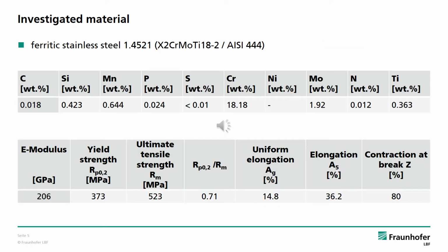This brings me to the results of the investigation. Investigations were carried out on a ferritic stainless steel 1.4521, for which I have summarized the chemical composition and material properties on this slide. With a tensile strength of 523 MPa, this material does not belong to the group of high-strength steels. From this point of view, this material should not show any particular susceptibility in combination with hydrogen. But more on this on the next slides.